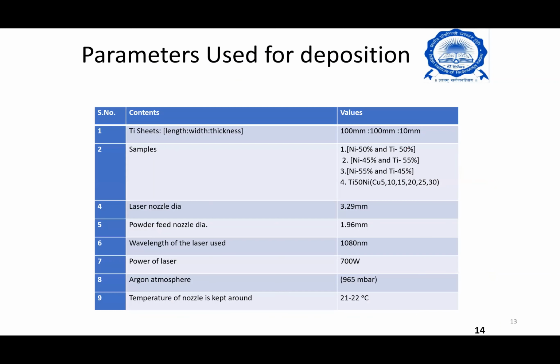The titanium substrate chosen for our experiment is expected to allow easy debonding, and it can also take care of the thermal expansion mismatch because of the difference in Ni and Ti. Prior to the experiment, we sandblasted the substrate to roughen the surface so as to increase the laser absorption. Argon gas was used as a shielding and carrier gas, and it prevented oxidation.